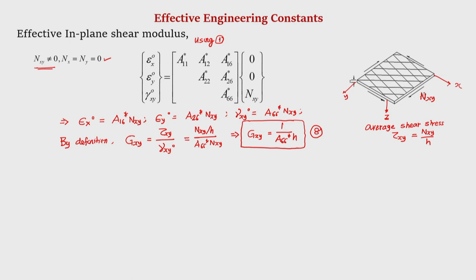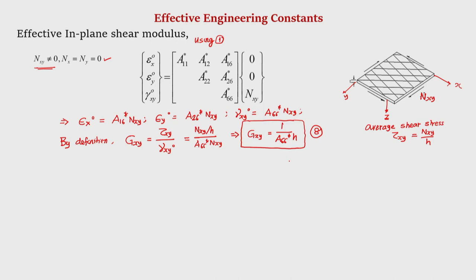Next, because it is a symmetric laminate, note that in all the cases when we have applied N_x, as a response to N_x there were epsilon_x, epsilon_y, also gamma_xy. Similarly, as a result of N_y, there were epsilon_x, epsilon_y and gamma_xy. That means, even though it is a symmetric laminate, A16 and A26 are present. That means there is in plane shear extension coupling. We could obtain the expressions for effective engineering constants E_x, E_y, G_xy, nu_xy under in plane load. Similarly, you can also find out the Young's modulus under flexure.